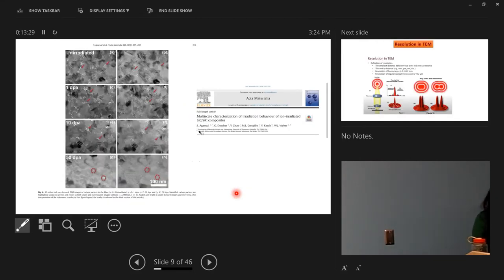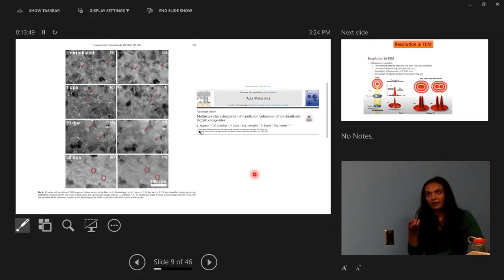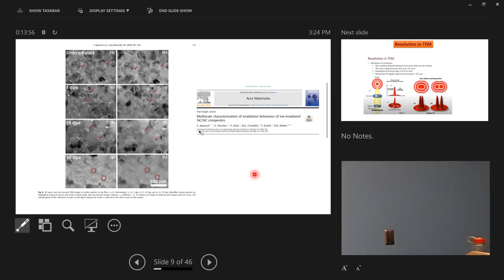Another example is a paper that I also published in 2018. There, we were not seeing bubbles, but we were seeing carbon packets. This is something that I did in silicon carbide. In silicon carbide, some extra carbon agglomerates to form these extra packets between the grains. Here on the screen, what you see is an unirradiated sample, a silicon carbide fiber, and you have extra carbon packets which are seen as these polygonal shapes which are white. Once I change the focus, they become black.